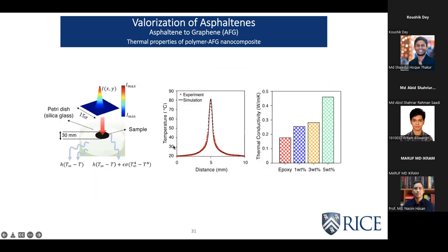So for that, we did a COMSOL FEA simulation, basically a simulation of laser heating with the laser having a Gaussian shape. And from this test, we can also obtain the single line profile. So we gave different types of material input. For example, here for epoxy, we gave the material input as the density of the material, then specific heat capacity, the other thermal coefficients, and we kept on tuning the thermal conductivity till the line profile obtained from simulation matched